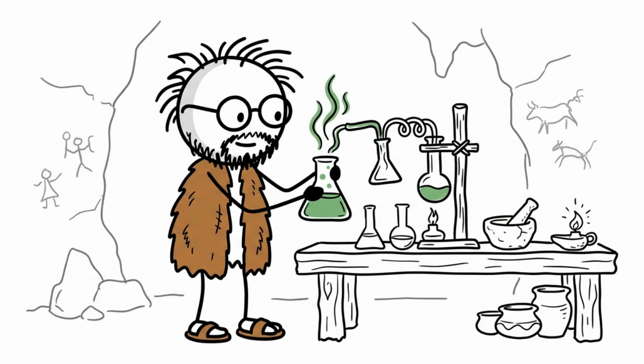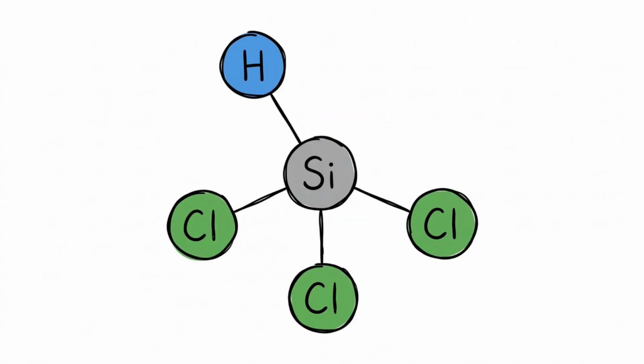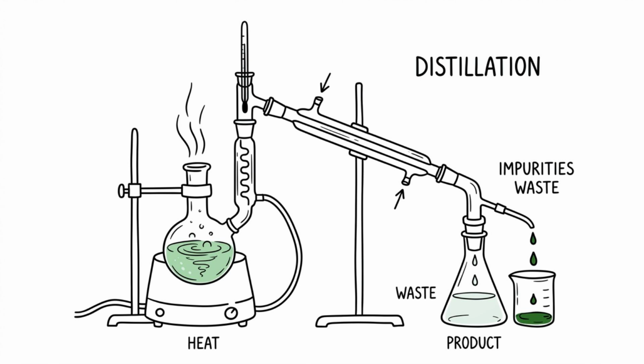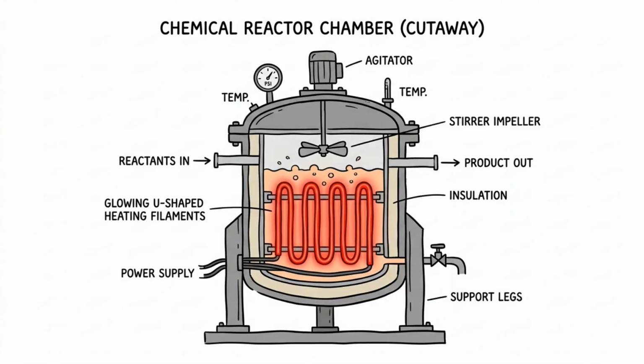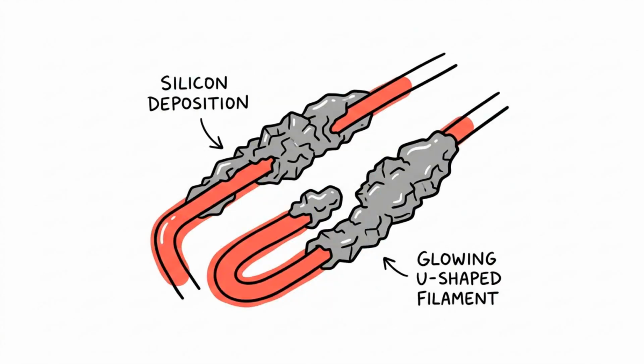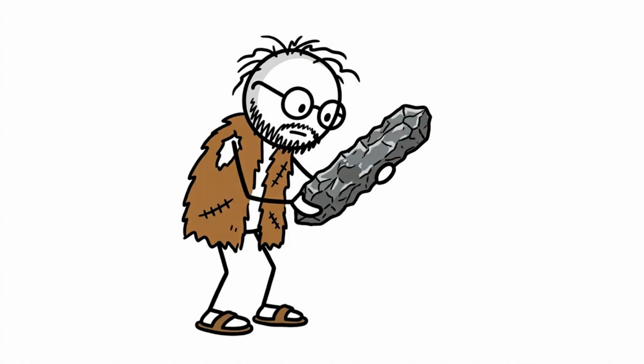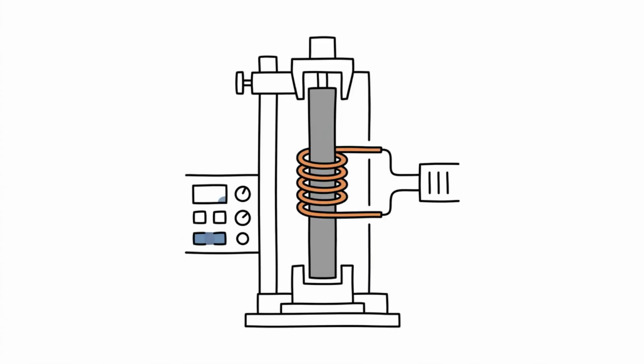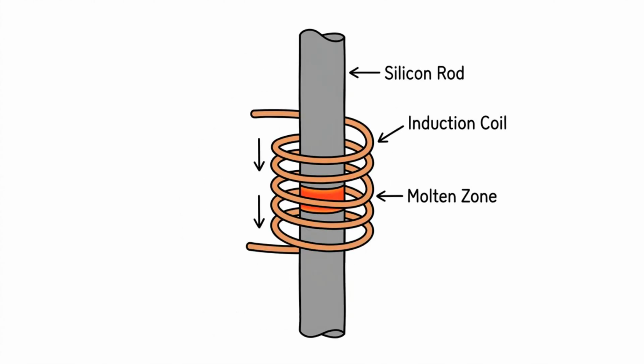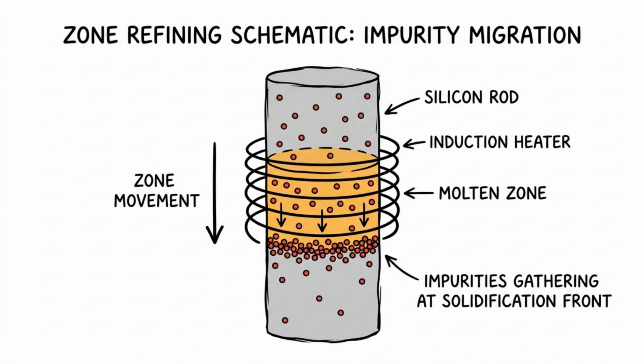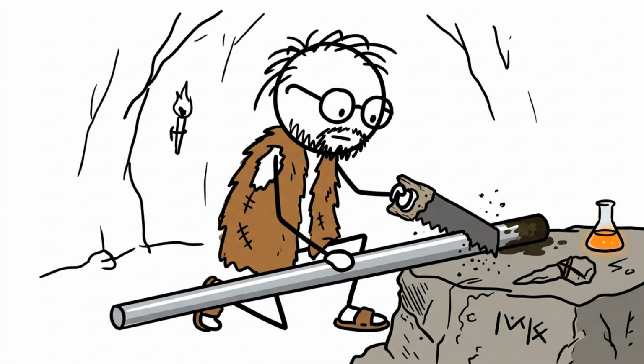To reach this nine nines purity, engineers convert metallurgical silicon into trichlorosilane gas. Distilling this gas repeatedly separates the pure silicon from contaminants, which is then deposited onto heated filaments inside a reactor. This chemical vapor deposition creates high-purity polycrystalline silicon. To push purity further, a float zone process passes a heating coil along a silicon rod. Impurities gather in the moving molten zone and are swept to the edge, leaving the rod incredibly pure.